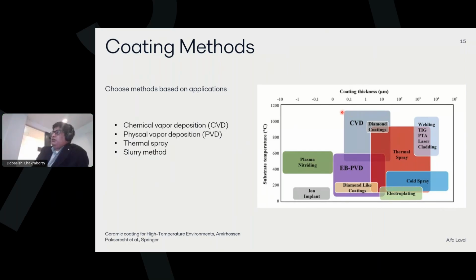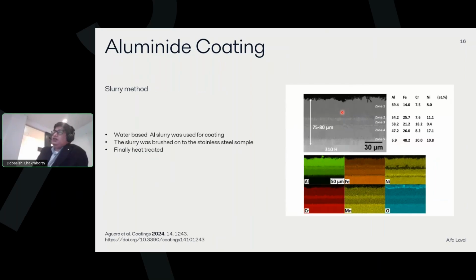But there are methods available. And then there is this slurry method where one could make aluminides. This is basically putting an aluminium layer on top of the stainless steel. And this layer could be thick or thin, depending on how you want it. But here it's like 75 to 80 micrometer thick.